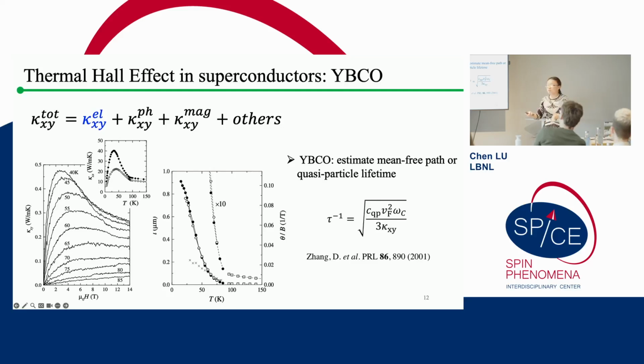about 20 years ago, people found the thermal Hall effect is a very powerful technique that can be used to detect D-wave quasi-particles which live deep inside the superconducting state. And apart from that, people can go directly from the thermal Hall effect data to estimate the mean free path for the D-wave quasi-particles in these cuprate materials.